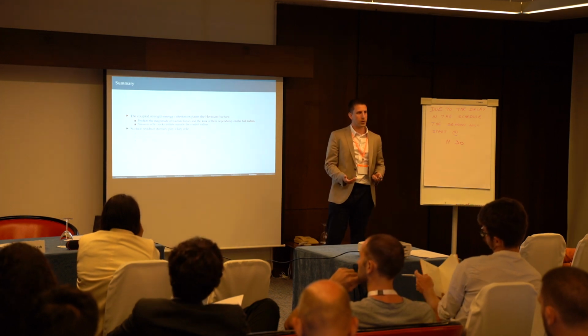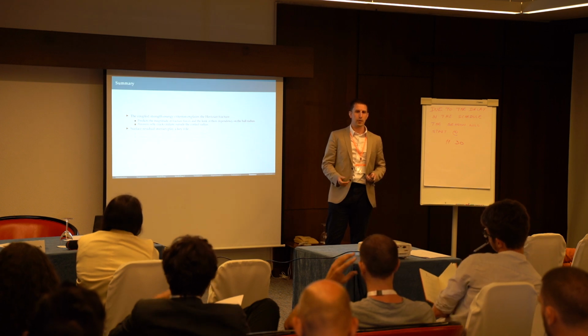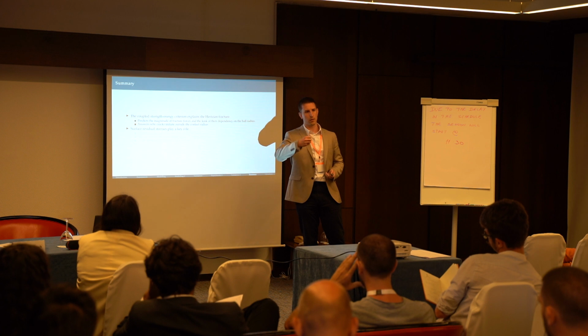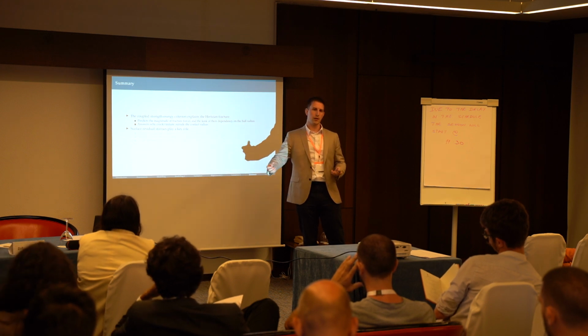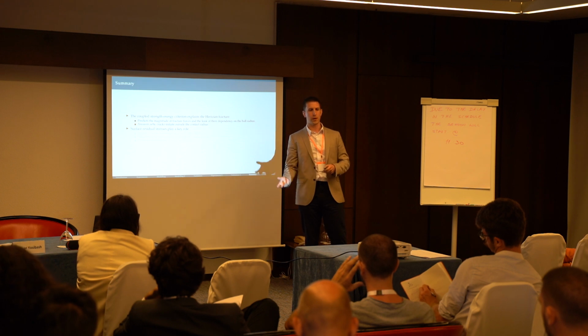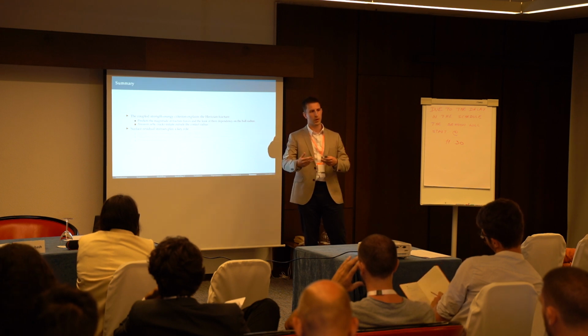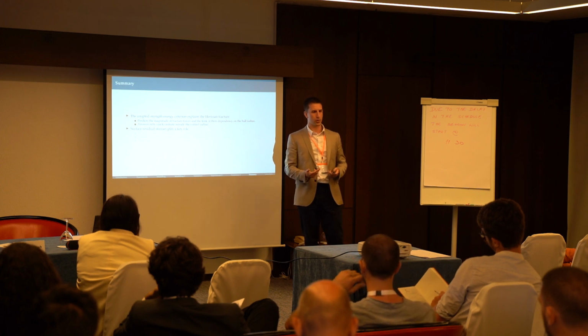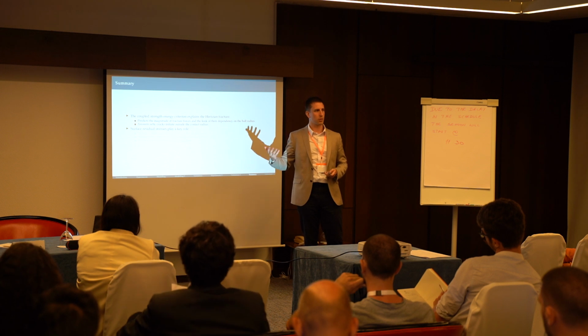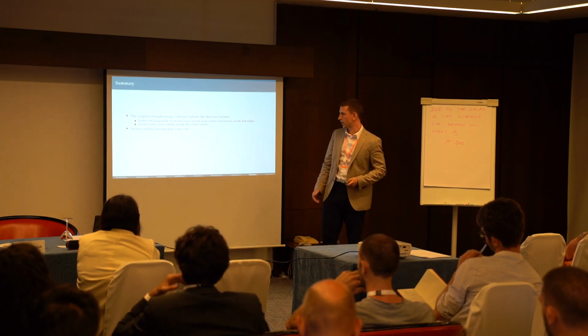If we do not have the measurement of the residual stresses, we can use different ball sizes, get the critical forces, then try to match the residual stresses which would make sense, and we can compare later with the experiments. So it is a hypothesis, that the residual stresses are causing that, but it is a hypothesis which can be disputed, so we can work with it.